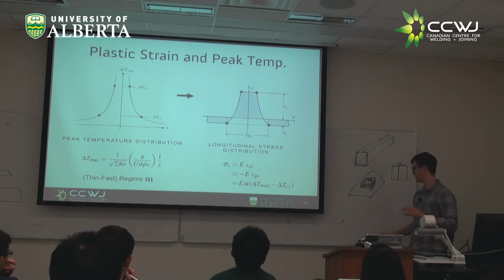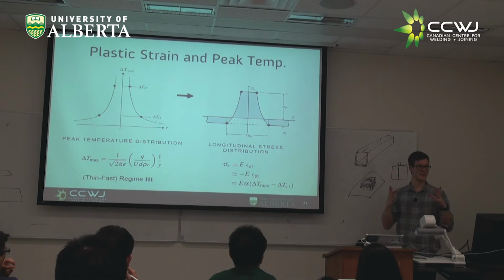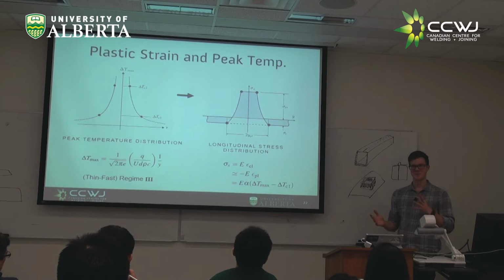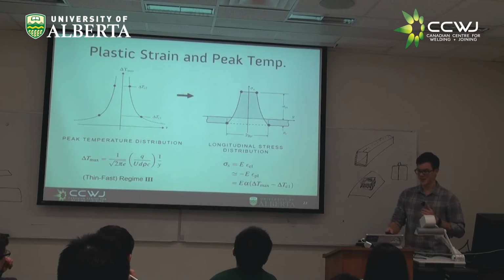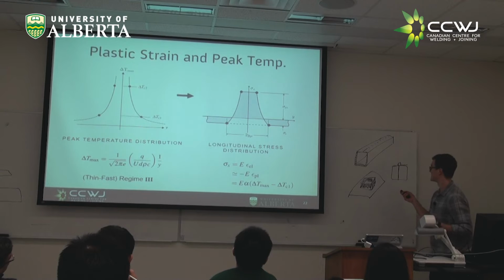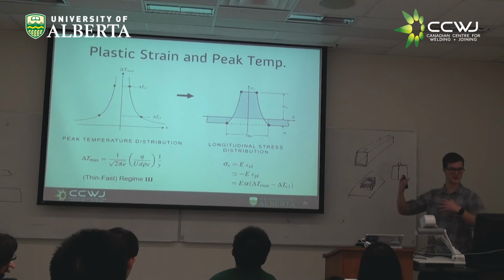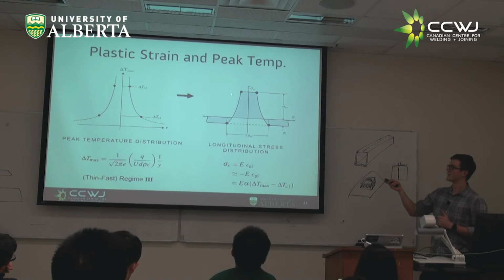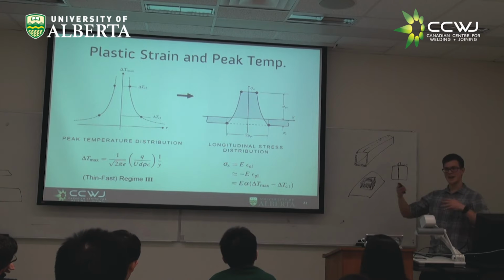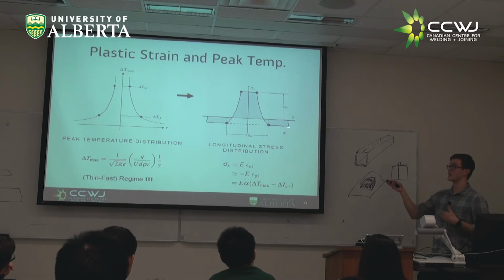So we kind of do a little bit of a cheat there where we're going to ignore the compressive stress in order to calculate how big that plastic strain block is and how big those tensile stresses are. And then we'll use those tensile stresses again to calculate how big that compressive stress is. So we're not perfectly consistent, but we've taken what would be a really complicated problem where we have to deal with the fact that as this is developing plastic strain, it's also shrinking. And we've made it somewhat more manageable by saying we're going to ignore this initially. We're going to figure out what this stress is. Then we're going to apply that stress to a free plate, figure out how much it shrinks, and use that just to shift the stress up and down to make sure we're at equilibrium.